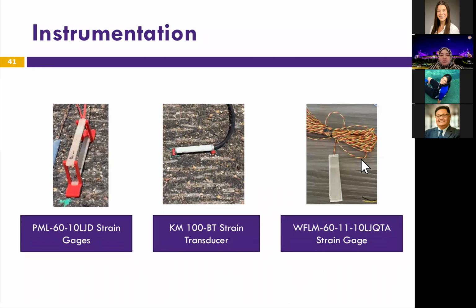All the sections are instrumented. So this slide shows the instrumentation that we used in the field study. We installed 3 different types of strain gauges during construction. The first 2 types were used at mid depths. And we put 2 of each sensor at each location for redundancy in case one doesn't work. The third type was placed at the bottom of the layer to make sure it doesn't move during construction. And as you can see here, we printed 3D supports for all the sensors so that they stay in place.